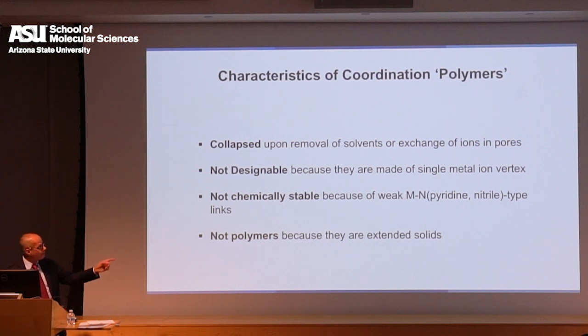So these structures that I showed you from previous to MOFs, they collapsed. They were not designable. This becomes very important in reticular chemistry, is that they are made from vertices that are single metal vertices, not aggregates. The carboxylates aggregated the metal, so now you have clusters that can direct the structure for you and make a stable structure. They're not chemically stable, and they are definitely not polymers. They're actually a misnomer.